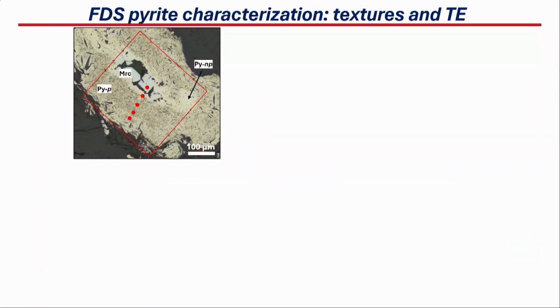So in this image, we also can see the different relationships throughout the pyrites. Here we have a porous pyrite vein, but we have some areas that still have some non-porous pyrite, and marcasite as well, which is growing in open spaces, which is the middle of the vein. We have done some laser ablation mapping, which is in the square in red, and some spots also with laser ablation, which are in red as well.